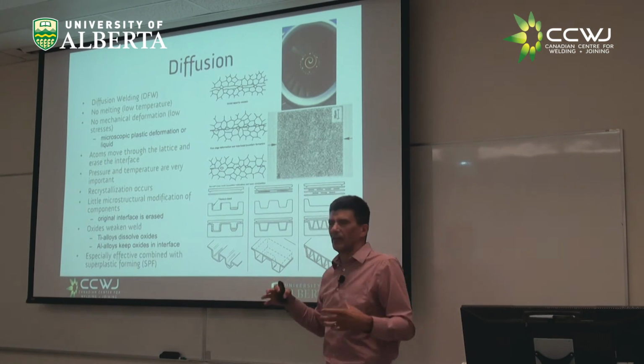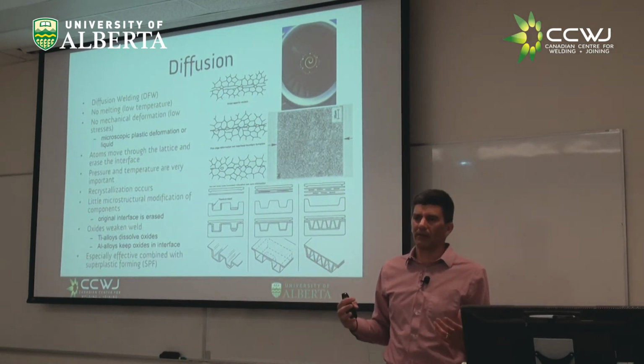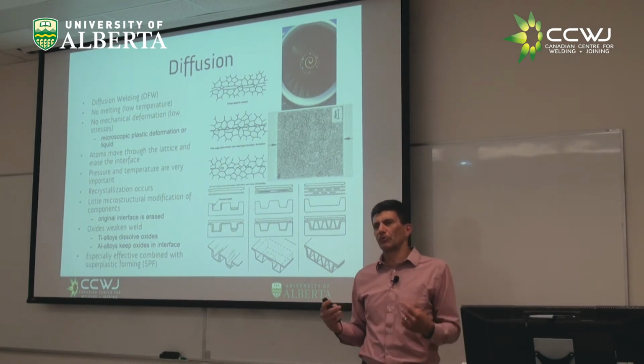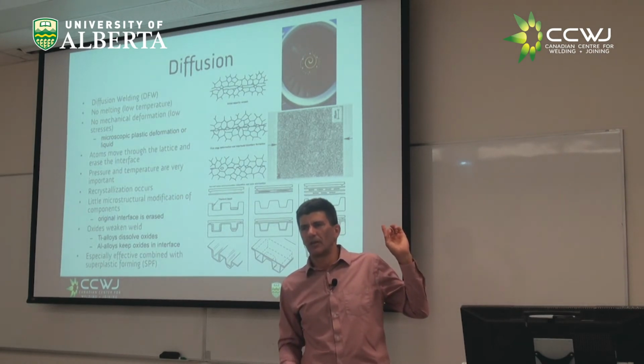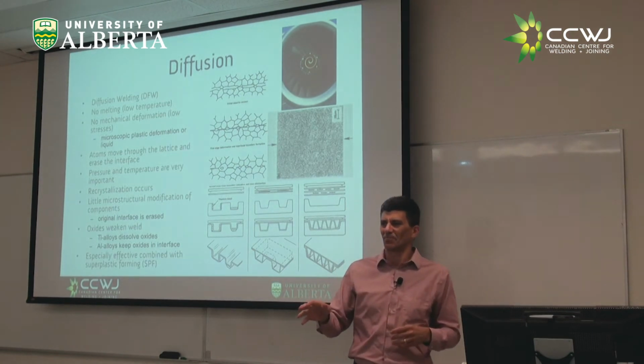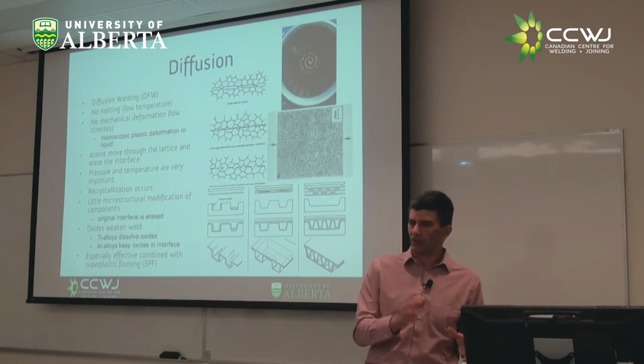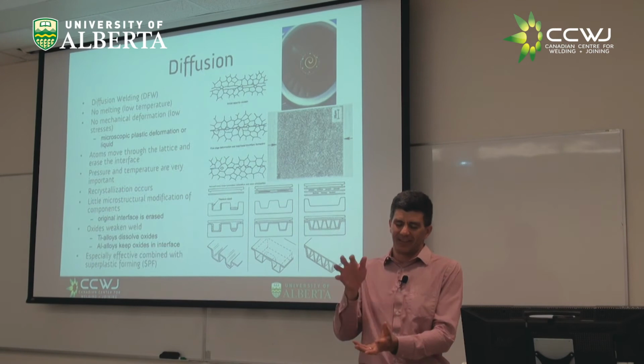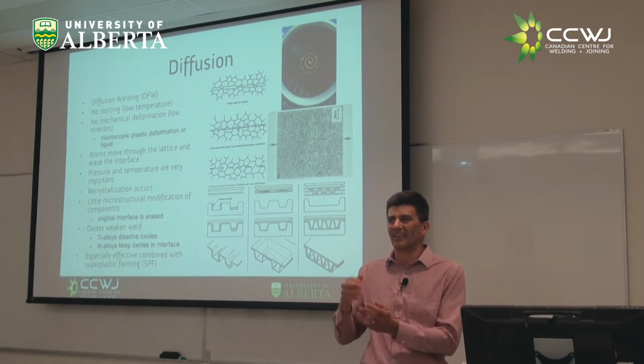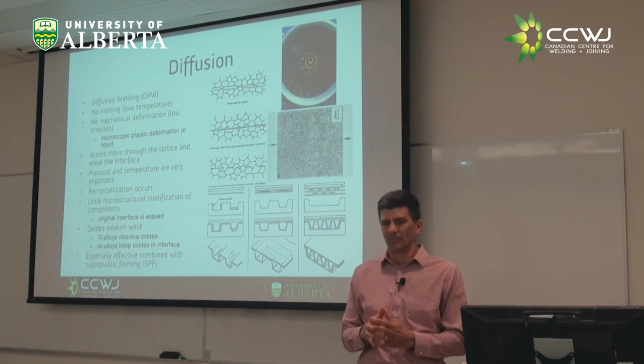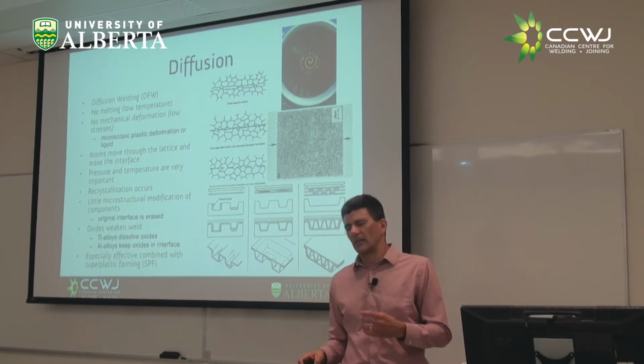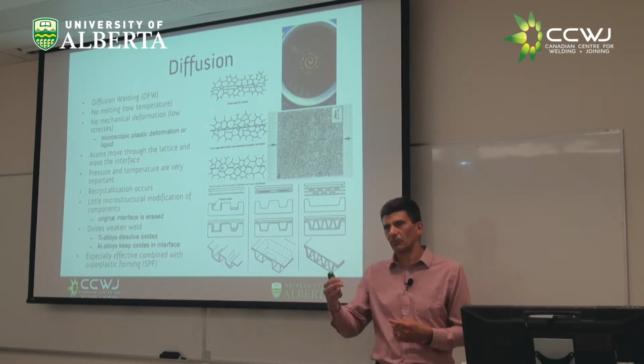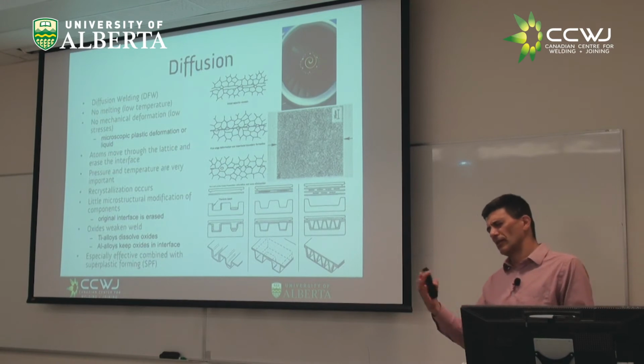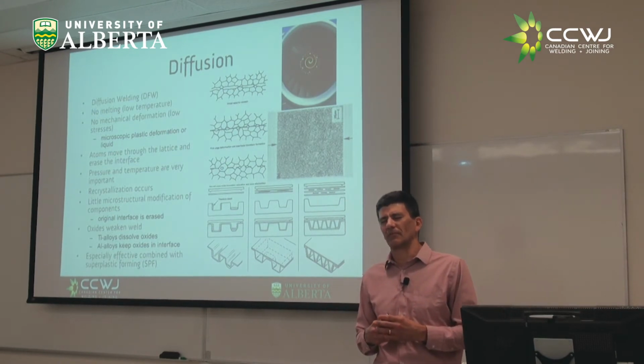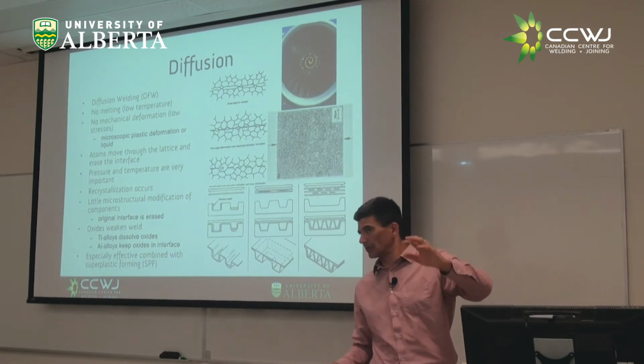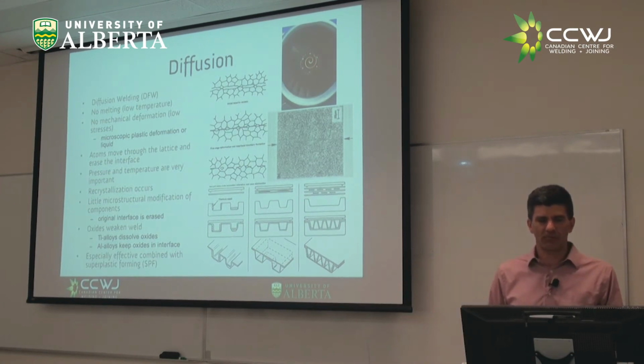You see this front fan of a passenger plane, right? Now it's not so much true, but in the past, Rolls-Royce used to make those front fans out of titanium, while GE was making them out of carbon fiber. And it was very interesting. The reason is that the guys in the UK at Rolls-Royce developed the technology for superplastic forming and diffusion bonding of the front blades of the front fan of passenger engines, right? And it worked very well. So the older Rolls-Royce engines are made out of titanium, while GE was making them out of carbon fiber. Now Rolls-Royce is also moving into carbon fiber. But these are very different approaches. And the whole approach of Rolls-Royce, which is not a little company, was based on this diffusion bonding.